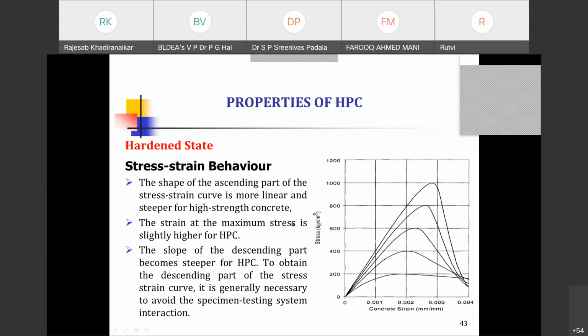The descending part also, you'll find that there is a difference in the post-peak behavior. This is what is called a snapback behavior, wherein you have a very extended stress strain curve for lower grades, and as you increase the grade, the post-peak behavior is different. The slope of the descending part becomes steeper for HPC. So you'll find that this is steeper compared to this.